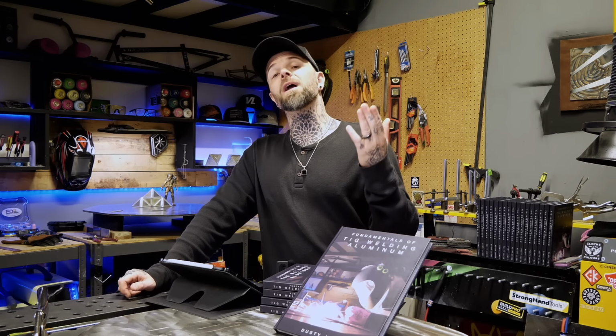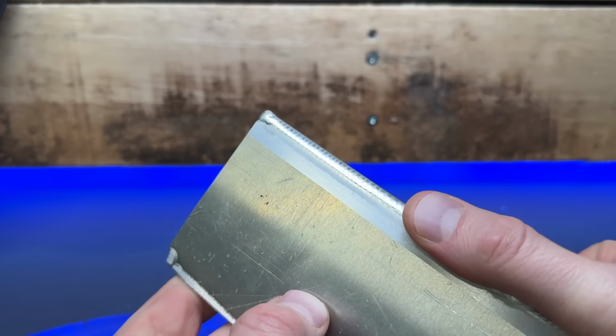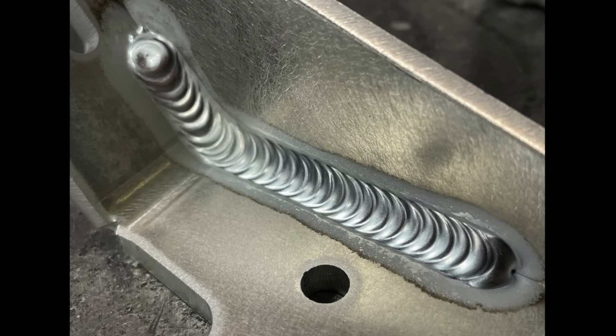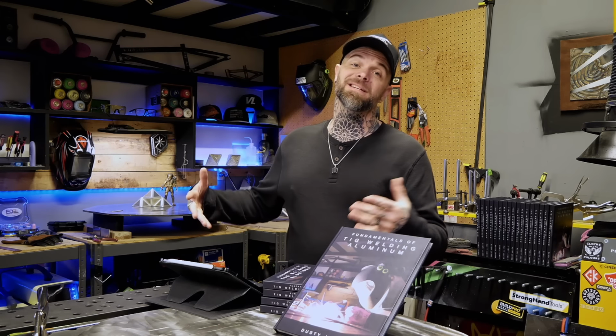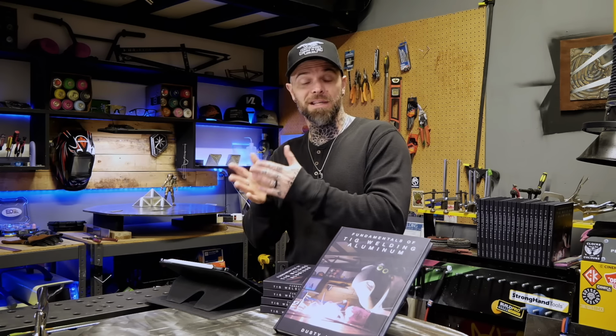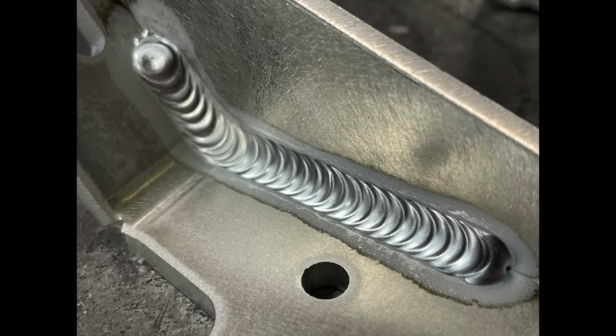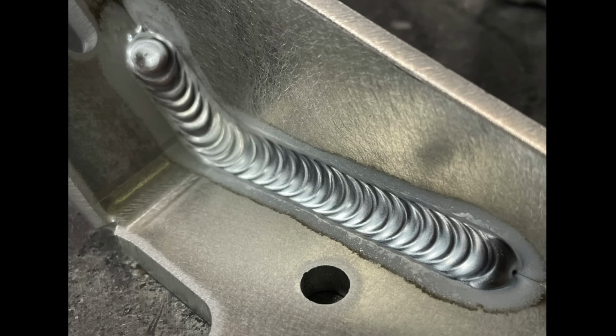So let me ask you, what if I'm doing a project like this here, or a welding exercise like this here, where the material is pretty thin? We want to do some nice outside corner work like this here. We need the arc to lock on perfectly, but then we've got to transfer over and work on some thicker material like this here, like some heavier welding, like a fillet joint inside of some plate that's a little bit thicker. What's going to happen is if I set my balance on my machine so that I keep a pointed tungsten perfectly, when I'm welding on this stuff, it may work absolutely fine. But then if I flash up with the same electrode on something thicker like this, the tip of the tungsten is going to be under more stress because of more amperage requirements, and it's very possible and most likely that the tip of the tungsten is going to wobble around like it's on its 10th beer at a Nickelback concert.